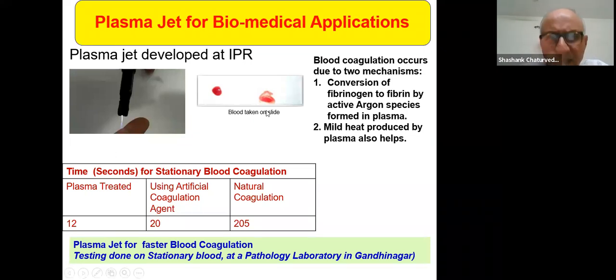Now, one of the applications amongst many is that it can help in faster blood coagulation. So basically, if you have bleeding somewhere, we've done testing at a pathology lab here. Natural coagulation of blood can take up to about 3 minutes. Using artificial coagulation agents, you can bring it down to 20 seconds or so. With plasma treatment with a jet like this, it can come down to 12 seconds. We're still trying to understand the mechanism there, but we're trying to see whether this could become something which could be used by, say, first responders. If you have an accident or something like that, can they use it to stop bleeding?